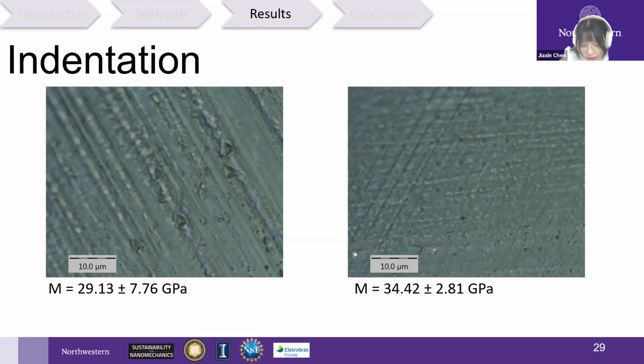Using the Oliver and Pharr method, we have our indentation modulus for air embedding of 29.13 plus and minus 7.76 gigapascal and 34.42 plus and minus 2.81 gigapascal for vacuum embedded specimen. In terms of indentation modulus, M represents the indentation modulus. And if we assume the Poisson ratio is 0.32, which is what Professor Moore et al. did in their paper, compared to their results, we have a really good agreement.